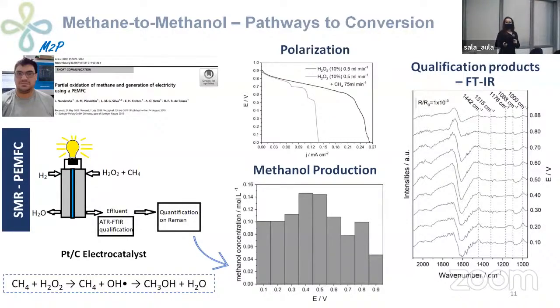So with the electrocatalyst of platinum supported on carbon, we observe the formation of hydroxyl radicals. Here, the authors observe there is a synergic effect on this formation, the reactive oxygen species attack the methane to form other products such as methanol. And here we have the quantification of methanol production.